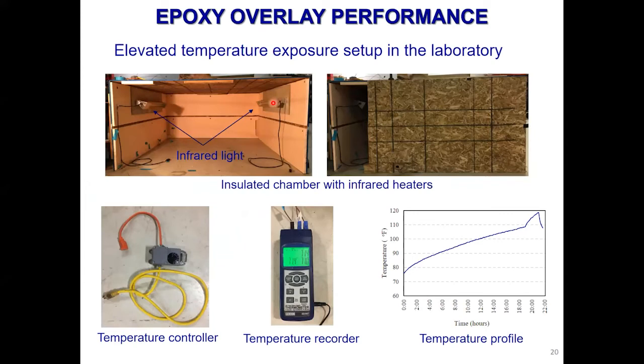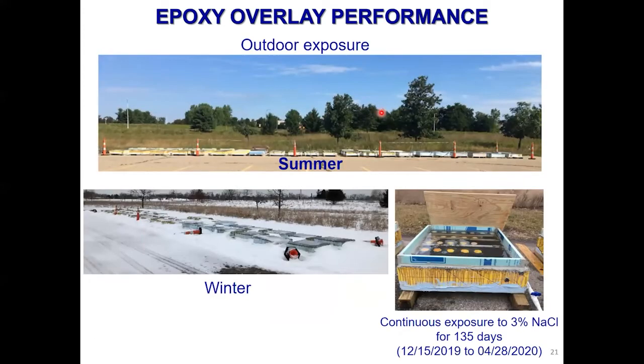In the lab, we use infrared lights to heat up the slabs. This is showing how the temperature is going to increase in the slabs with multiple lights. And then we get the slabs. These are almost 4 feet by 4 feet, 9 inch thick slabs with overlay applied. There were like 50 some slabs. They get exposed to summer and winter conditions as well as 3% chloride during winter.